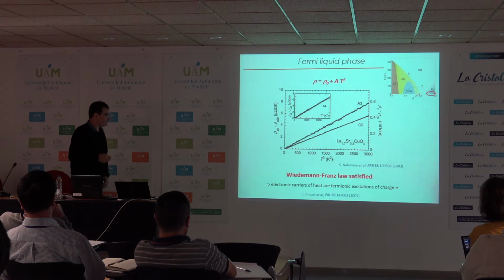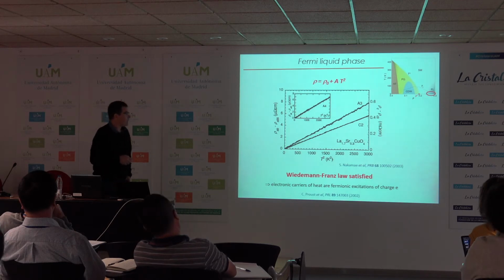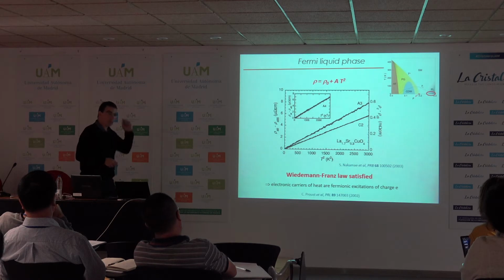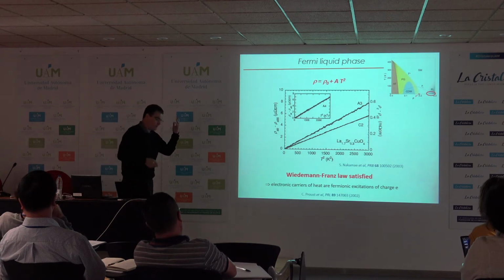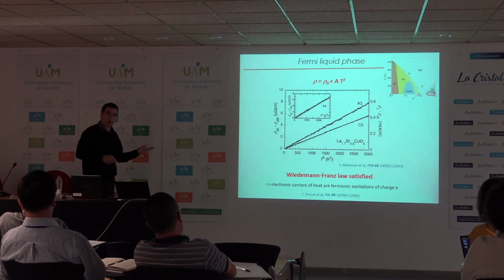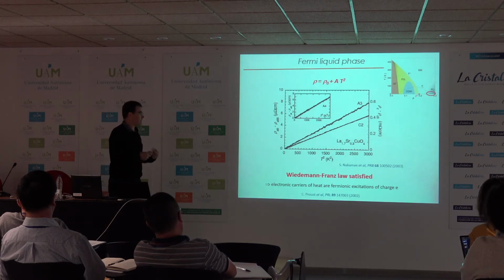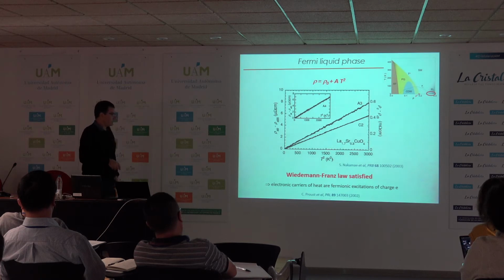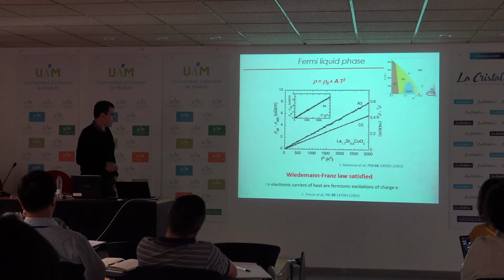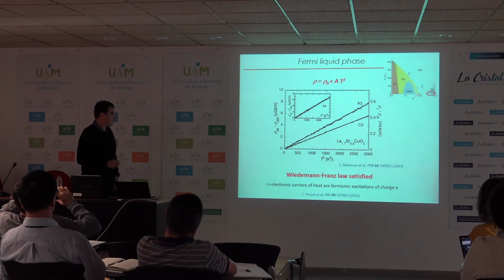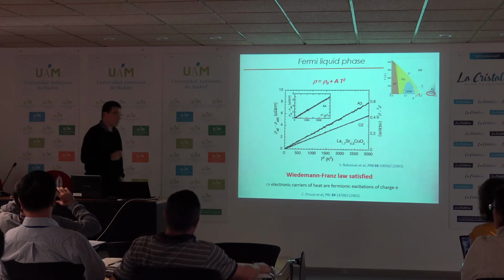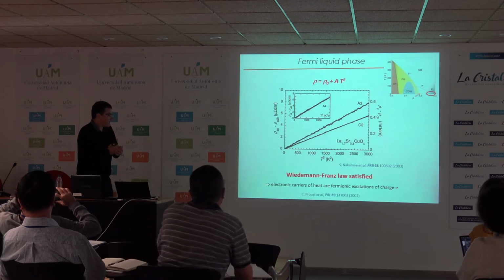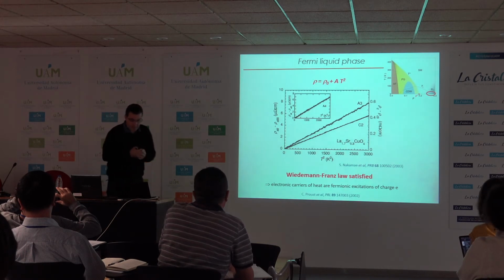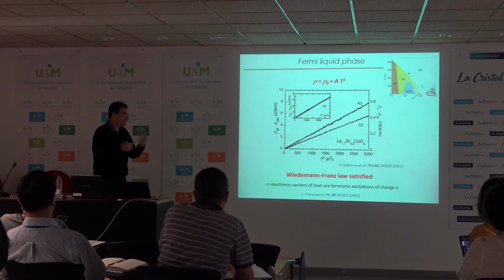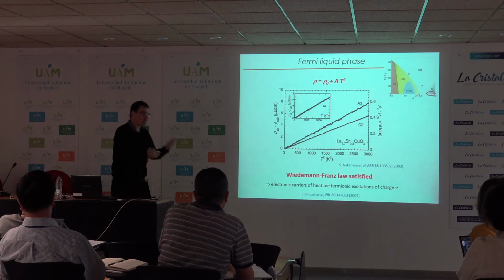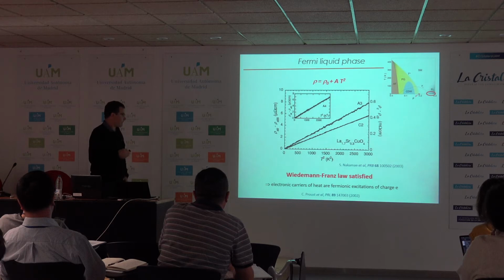A second signature of Fermi liquid is the Wiedemann-Franz law, and to do this measurement, you have to measure the thermal conductivity and the electrical resistivity on the same sample with the same contacts. More than 15 years ago now, we showed that this Wiedemann-Franz law is beautifully satisfied in strongly overdoped Tl2201, meaning that the electronic carriers of heat are also the fermionic excitations of charge e, so the electrical current is transported by the same charge carriers as the thermal transport.